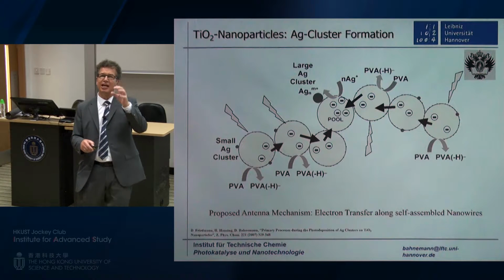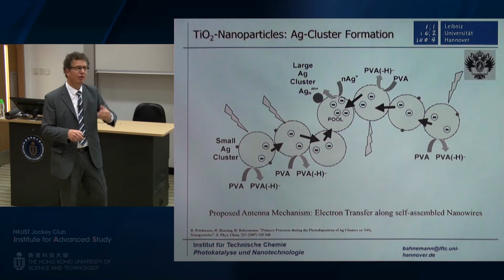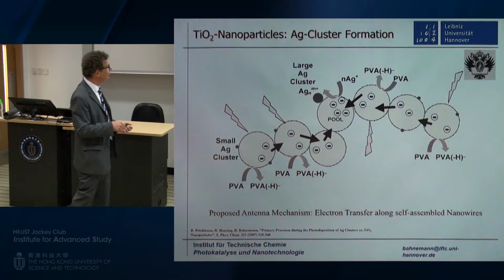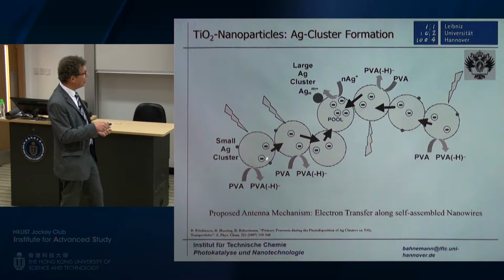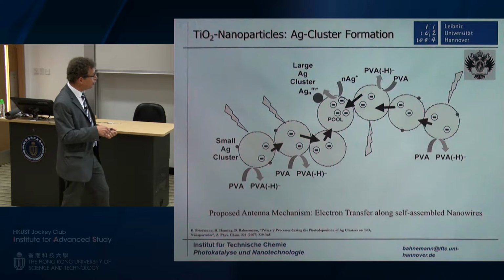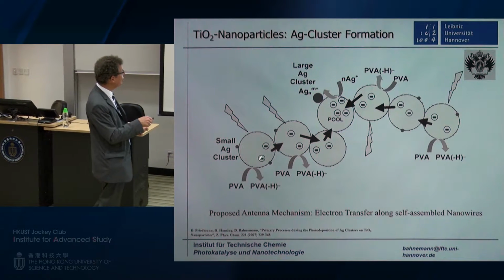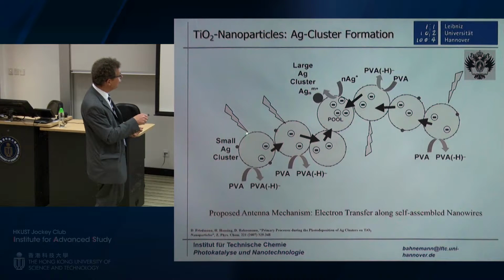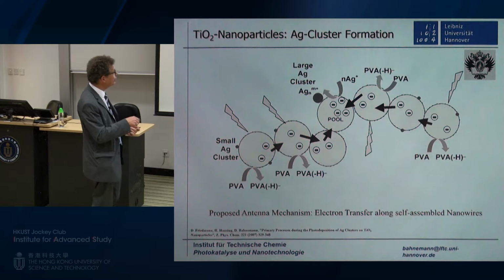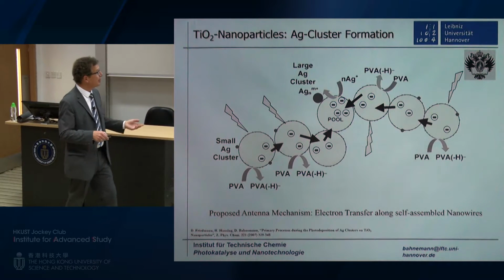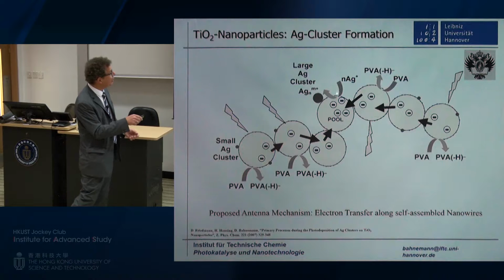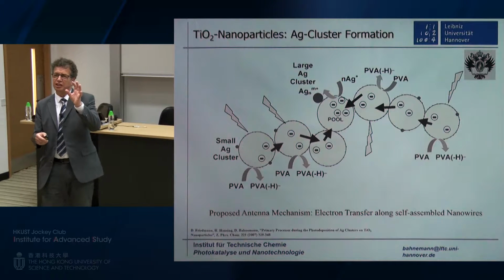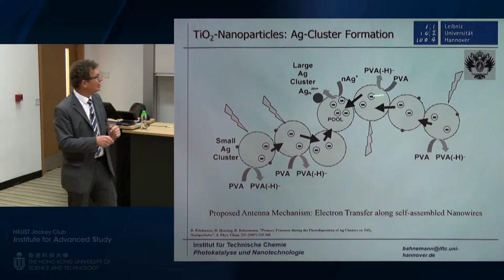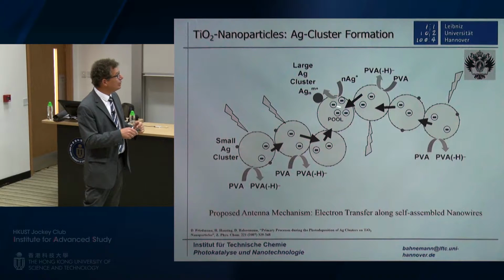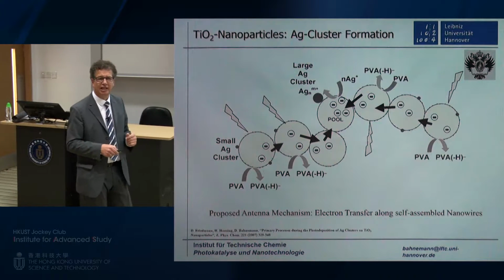intermediate radical is now a very good reductant, even a better reductant than the electrons that you form initially, and injects a second electron, being itself converted to the aldehyde, injects a second electron into the material, so absorption of 1 photon effectively results in the formation of 2 electrons per particle. And what we have seen is the formation of these rather large, I'm talking about 20 to 30 silver atoms, rather large silver clusters within a few nanoseconds of the laser pulse.